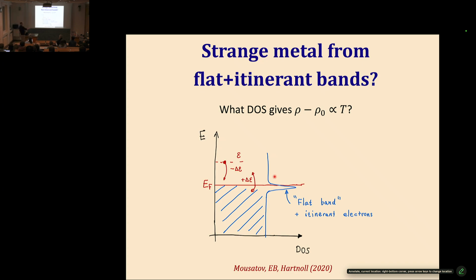If you run the same argument, you say I have a background of a constant density of states. Suppose I have a dispersive band, but I also have a flat band very close to the Fermi energy, or actually, let's put it exactly at the Fermi energy. You do the phase space argument for this case, and you find that the scattering rate of electrons from the dispersive band, basically one electron from the dispersive band and one electron in the flat band, the phase space for that scattering event is linear in energy or linear in temperature. Sorry, flat on a scale of kT? Yeah, it has to be flat on the scale of kT, and its distance to the Fermi level has to be smaller than temperature. Okay, so this is what you need.